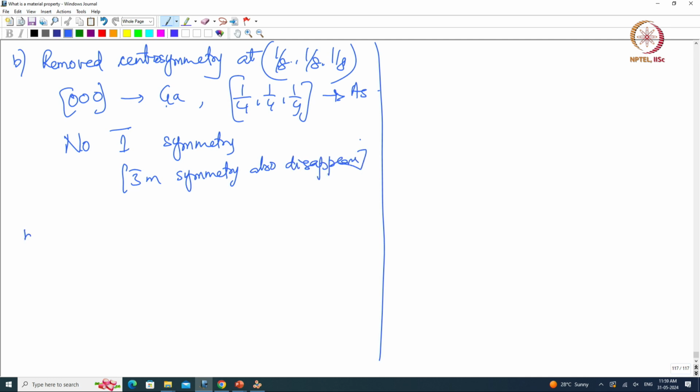Okay. So as a result, we have seen this earlier, zinc sulphide or gallium arsenide crystallize in a space group with the highest point group symmetry being 4 bar 3m. I do not have an inversion symmetry which is slightly displaced by one eighth, one eighth, one eighth. So I do not have a glide plane here. I have reduced the symmetry from Fd3 bar m to F4 bar 3m. So the highest symmetry point that is both in the point group as well as in the space group is 4 bar 3m.